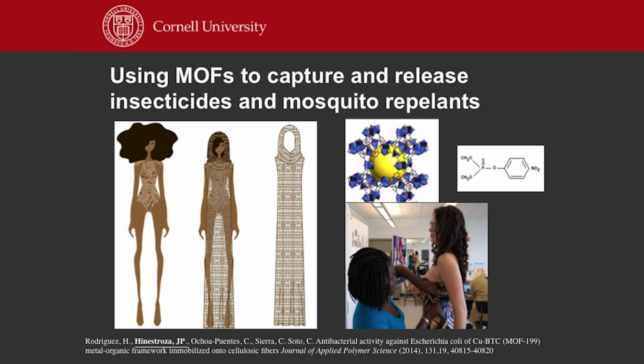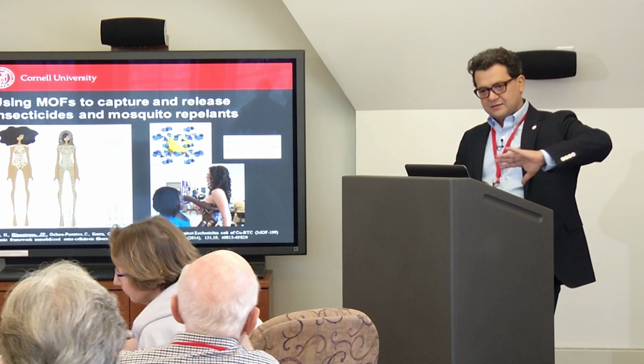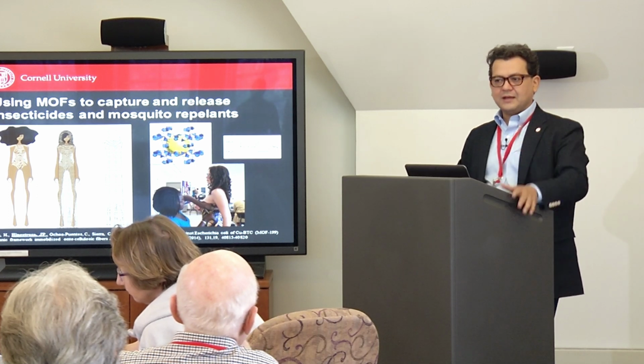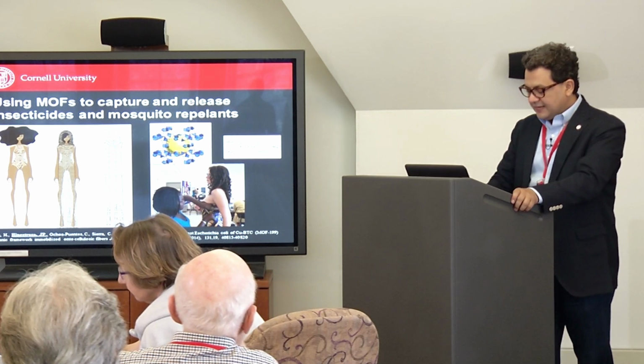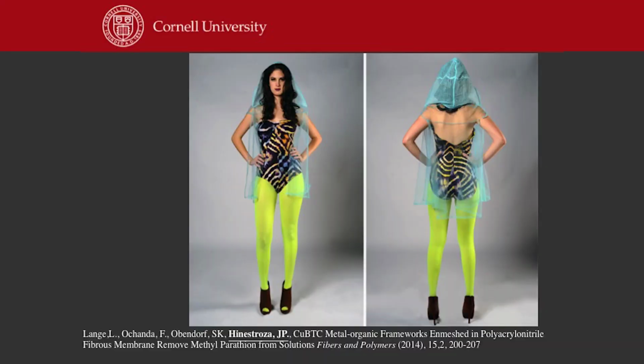And also, if you can make these ligands reactive to UV, then you can release the insecticide when the mosquito is more active. Instead of releasing it 24 hours of the time, you can release the insecticide depending on the light. Yeah. And that's what the student actually built. So the bikini is not part of the dress, only this part, the blue part, is where the insecticide is captured.